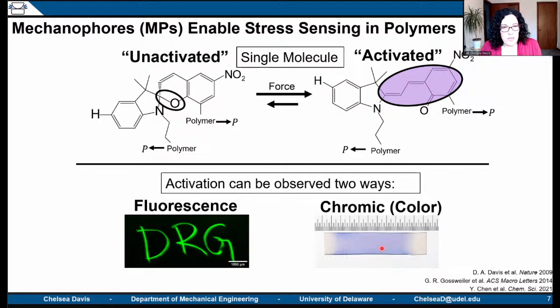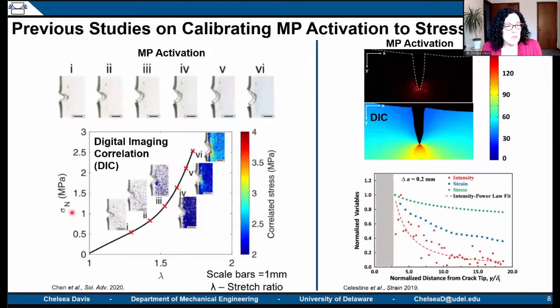And we weren't the first people to think about this. Several groups have used either digital image correlation, where you put a bunch of speckles onto your system and then track how those speckles move relative to each other in order to map a strain field onto your material. Or several other groups have utilized finite element modeling to calculate what the stresses should be within their material. And two of the first works that came out trying to correlate this stress response to the fluorescence intensity of mechanophores were looking at the stress concentration ahead of a propagating crack.